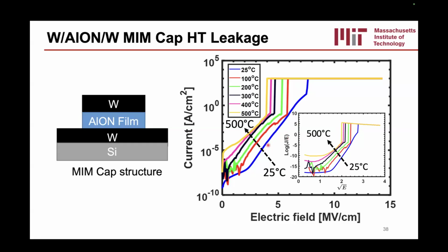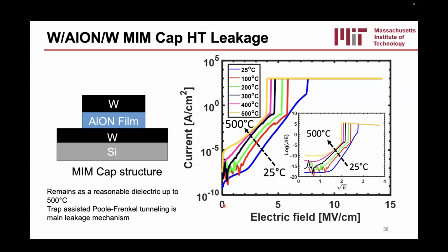You can actually see that the leakage we see here, if you plot it on a log of J/E versus square root of E scale, it increases with temperature, and you get straight lines here, which is indicative of a Poole-Frenkel like tunneling mechanism. So that's the main leakage mechanism for these films.